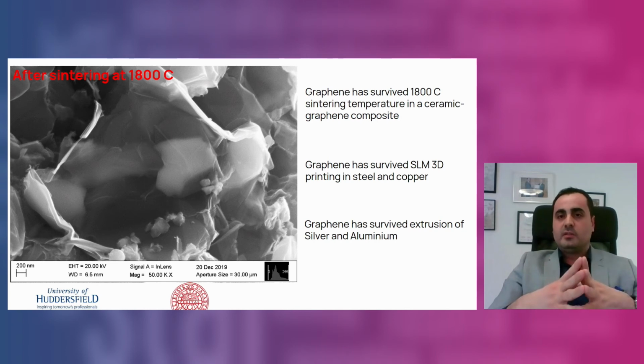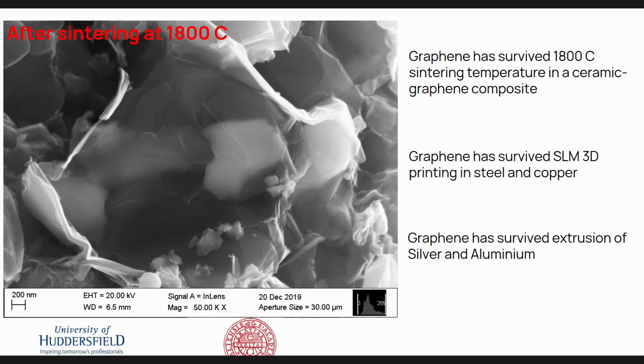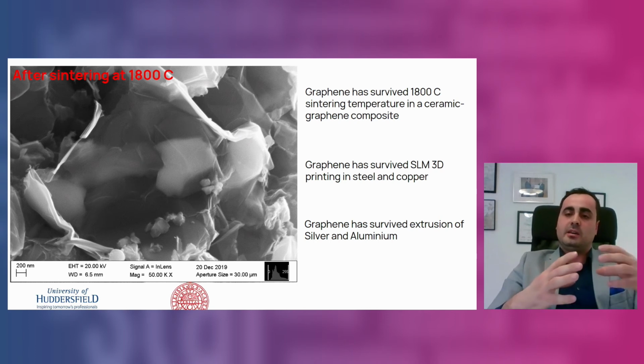has survived, for example, the sintering of ceramics, and this was 1800 Celsius degrees, survived the 3D printing of steel and copper, and the extrusion of both silver and aluminum. So with the data we have in hand, yes, we can tell that graphene can survive the processing of the metals and make metal graphene composites.